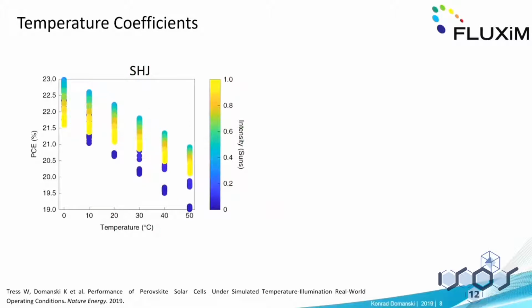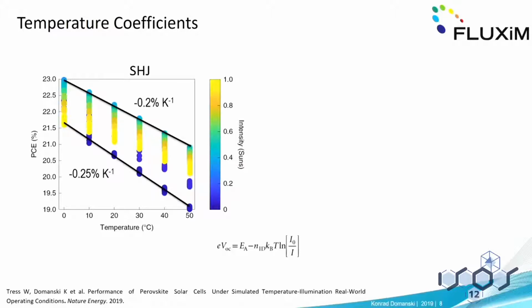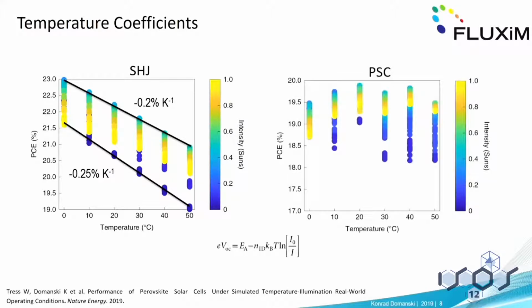So here I plotted the temperature effect on the efficiency a bit differently, and for silicon, you see that we get those negative temperature coefficients of 0.2 to 0.25% per Kelvin, which is what you would expect for a silicon heterojunction device. It's higher for PERC or more standard silicon devices. For perovskite, we didn't find anything, which is again a rather nice message because you would expect a drop. So we lose a little bit of VOC, but we compensate with higher fill factor. Probably because we have spiro-OMeTAD there, the transfer becomes better as you heat up the device because of the hopping transport, so you gain a little bit of fill factor, which you lose in VOC.